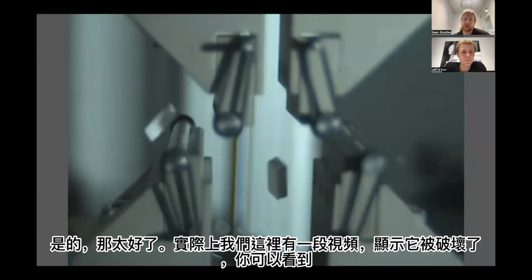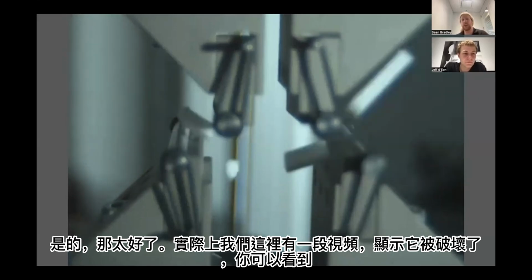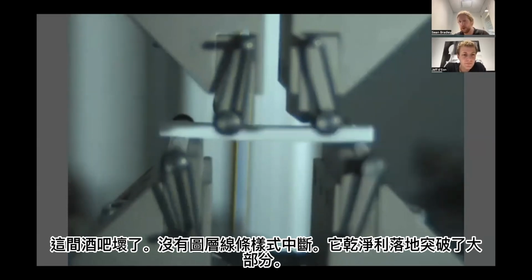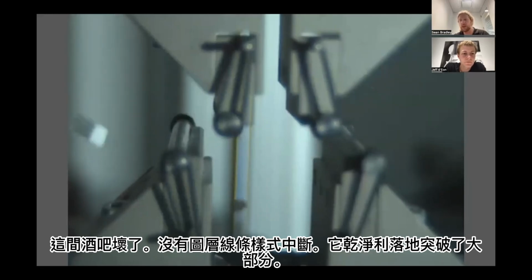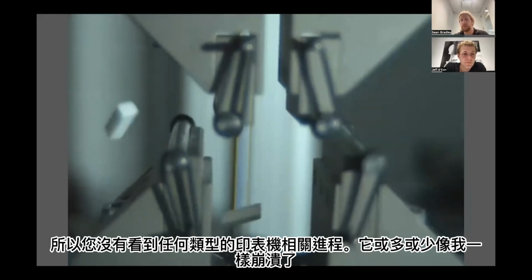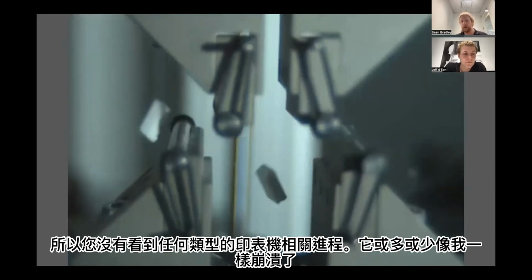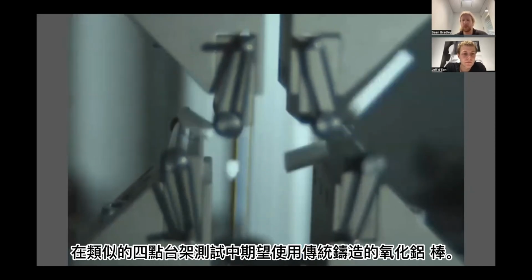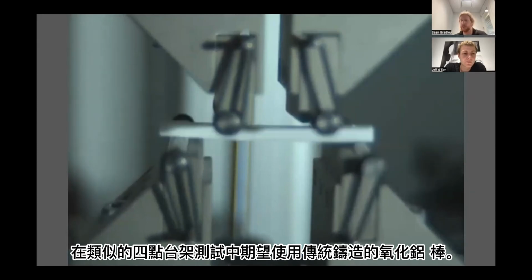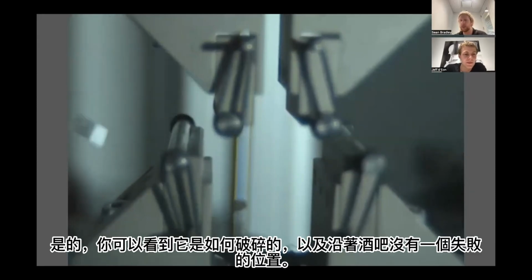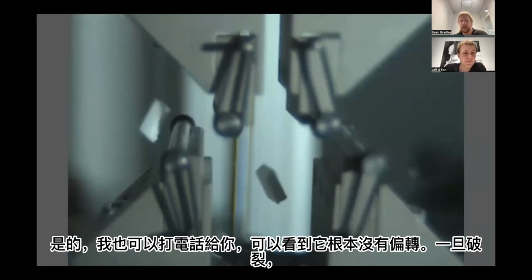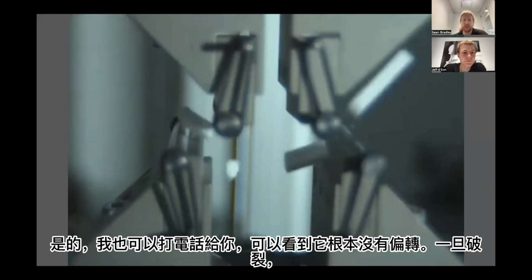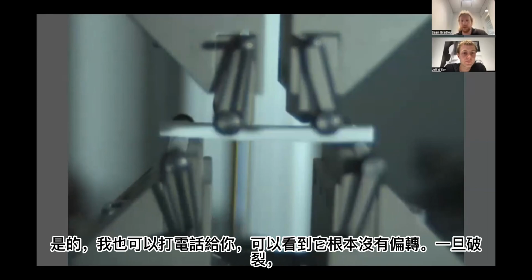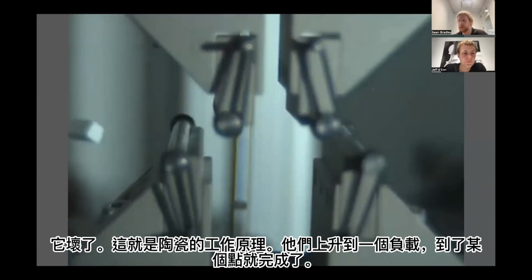Yeah, that's great. We actually have this video here of it breaking, and you can see this bar broke. There's no layer line style breaks. It broke cleanly through the bulk. So you're not seeing any kind of printer related processes. It's breaking more or less like I would expect out of a conventionally cast alumina bar in a similar 4-point bend test. Yeah, you can see how it shatters and how there's not like one location of failure along the bar. I can also call out that you can see that it doesn't deflect at all. Once it breaks, it breaks. That's just how ceramics work. They go up to a load, and at a certain point, it's just done.